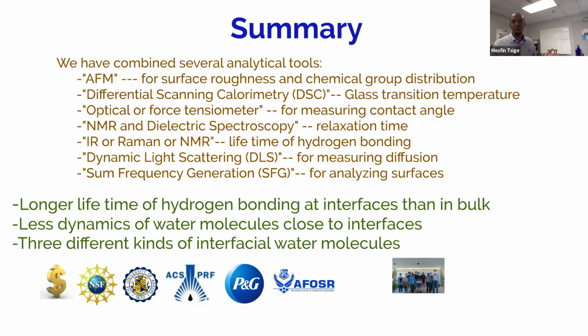For example, you have to use sum frequency generation or other spectroscopic approaches. All this is actually possible through our simulation approach, just by applying the statistical mechanics that we already know. And after combining all these different cases, we have observed longer lifetime of hydrogen bonding at interface than in bulk. The dynamics is much slower. And of course, we have observed heterogeneous interfacial water properties at the interface.